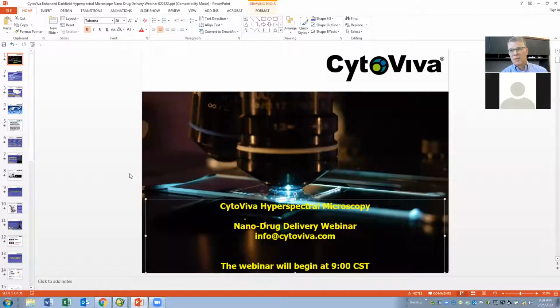So you can get some data, and if you understand your sample and its optical spectrum pretty well, especially with plasmonic nanoparticles, you can get some really insightful data relative to nanoparticle size, okay? And you can clearly see dispersed particles versus aggregates here. But any size information, for the most part, is qualitative. And it should correlate pretty well to what you see in your dynamic light scattering or NTA. If it doesn't, you might want to go to the ultimate nanoparticle sizing tool that's, of course, laborious to use, the electron microscopy. Okay.